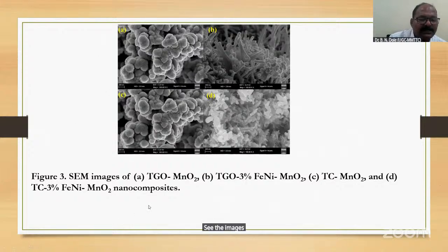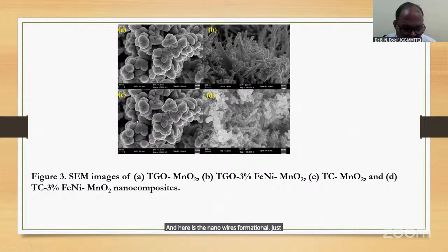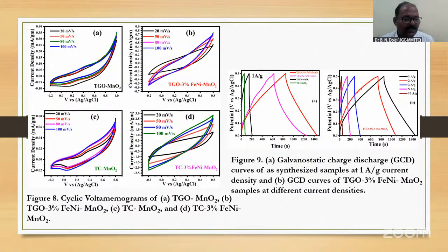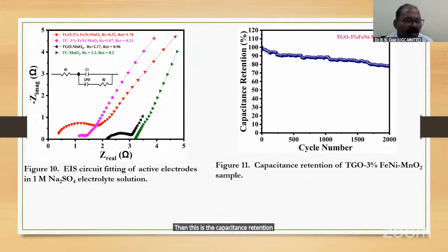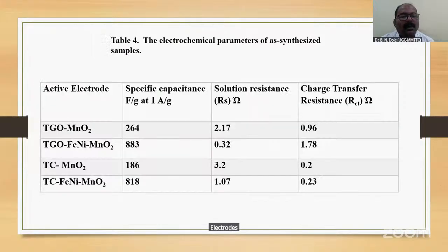See the images again. Same images. And here is the nanowires formation of the material, which shows its properties. Now this is the cyclic voltammetry. Okay. Cyclic voltammetry of TGO, MnO2, all these samples, and then the galvanostatic charge discharge. Means here the cycle we have to take. Then this is the capacitance retention. And this curve is the electrodes, electrochemical parameters of our synthesized samples, specific capacitance, solution resistance, and charge transfer resistance.